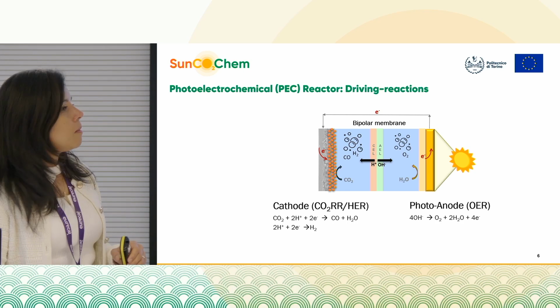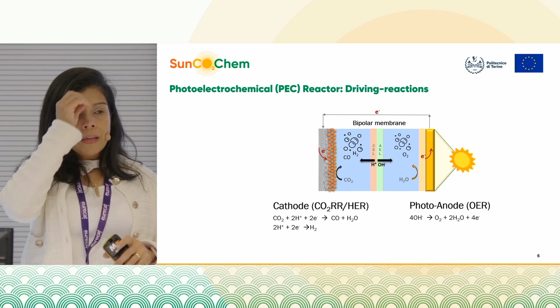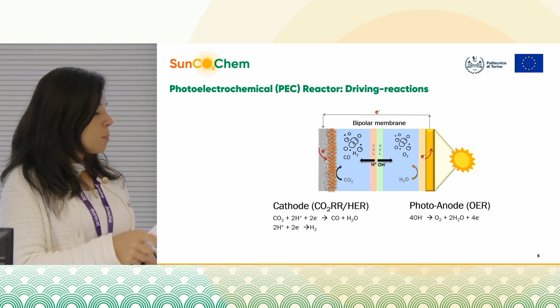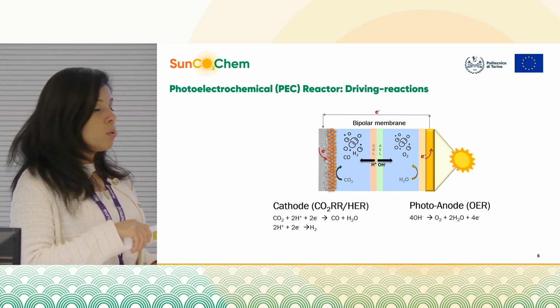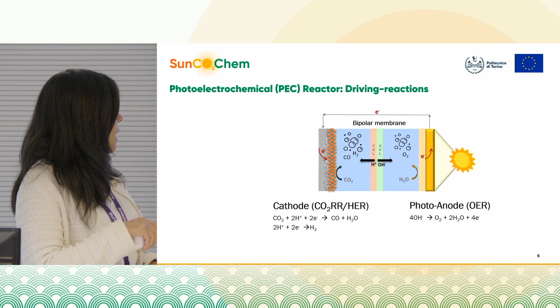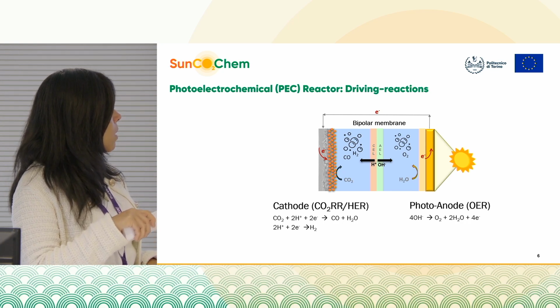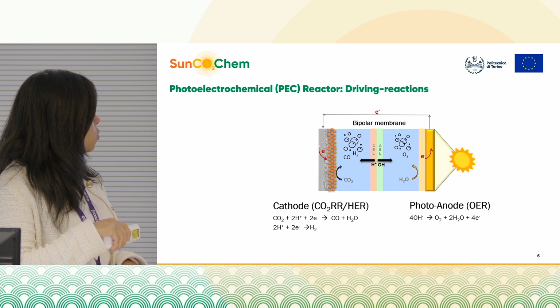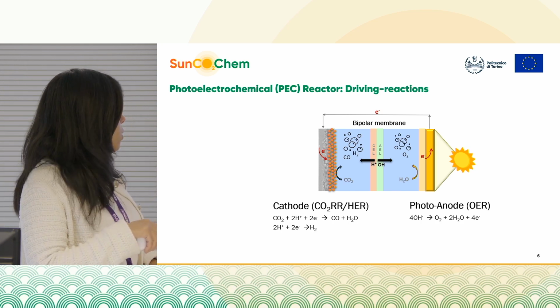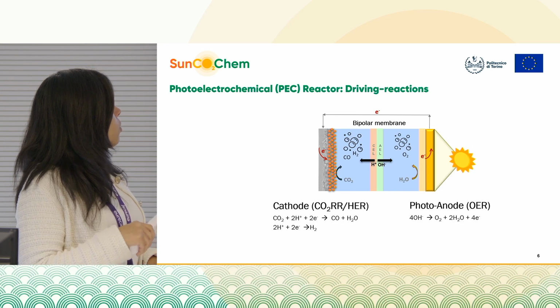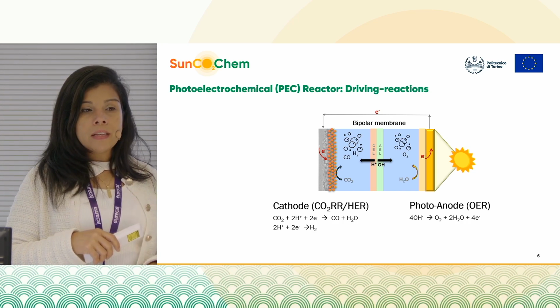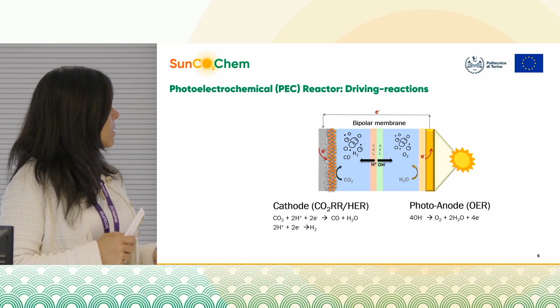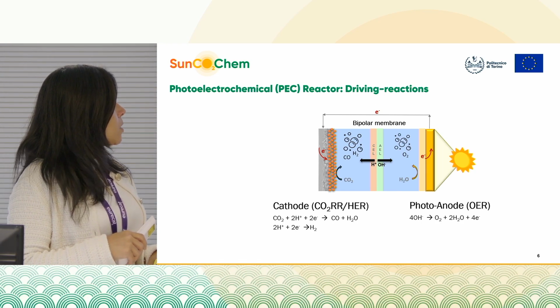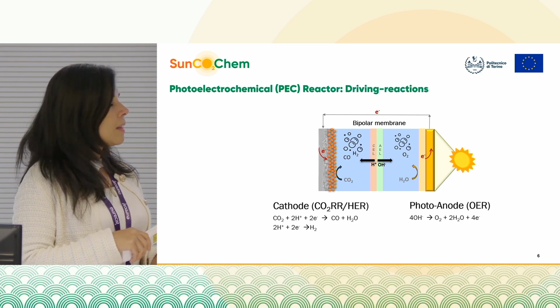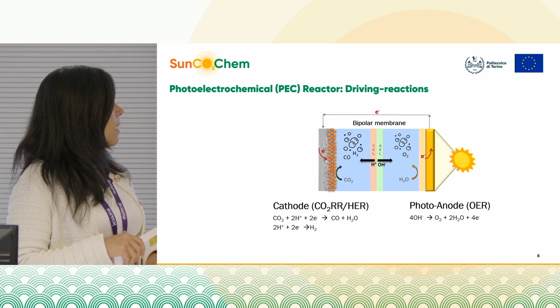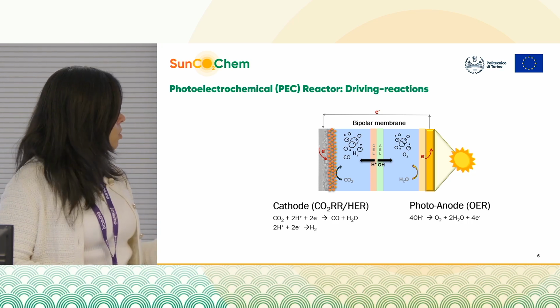So looking at our main photoelectrochemical reactor, the reactions that we want to perform here are at the cathode, the CO2 reduction to CO, to carbon monoxide, and obviously since we have protons coming from our bipolar membrane, we utilize those protons either for the CO2 reduction but also for the production of hydrogen. On the other side, in the photoanode, that is one of the sun-driven elements of our reactor, we exploited a bismuth-vanadate photoanode for performing the water splitting process and the hydrogen and oxygen evolution.